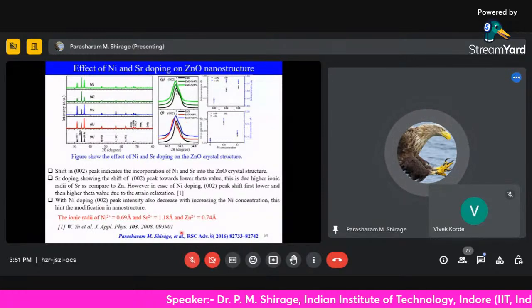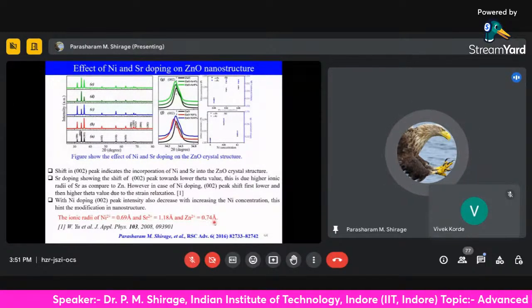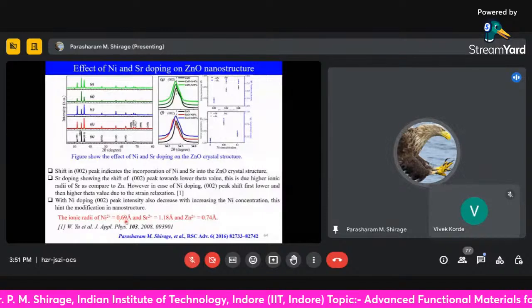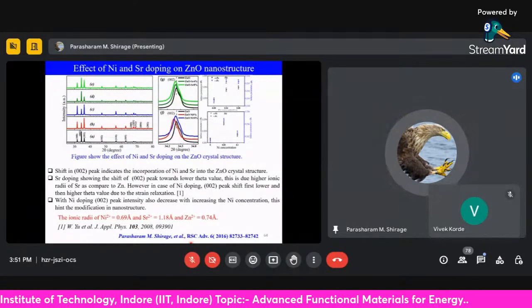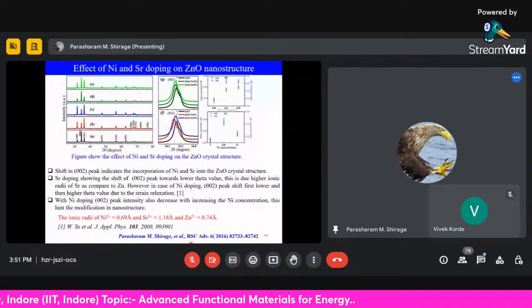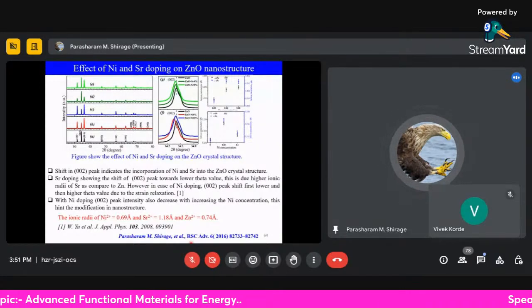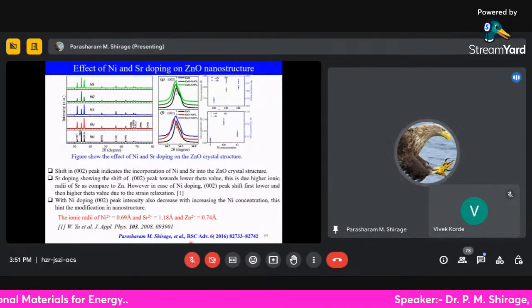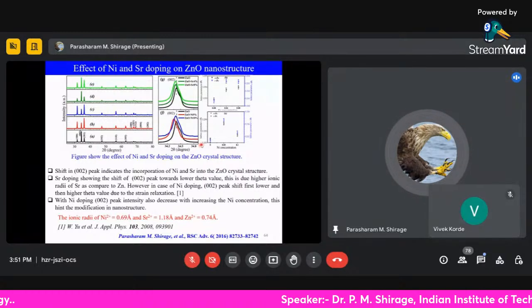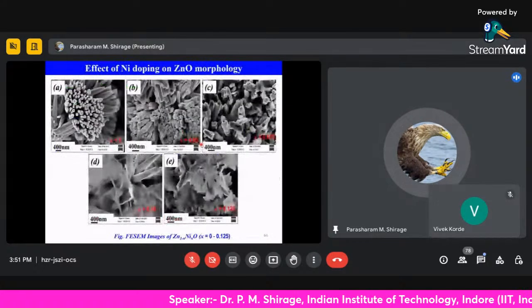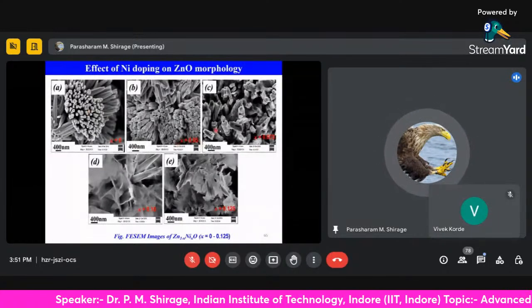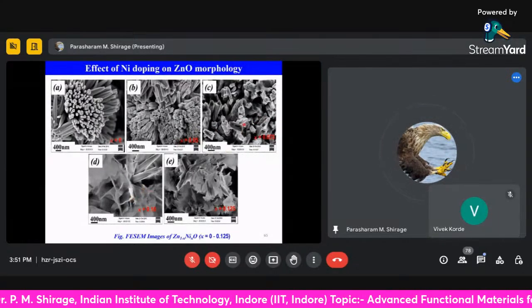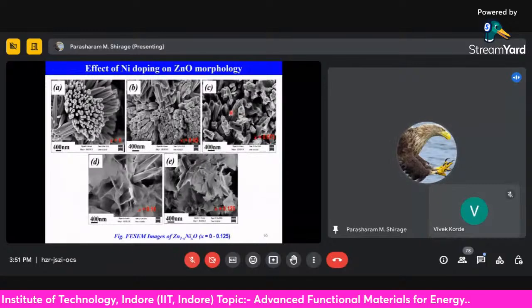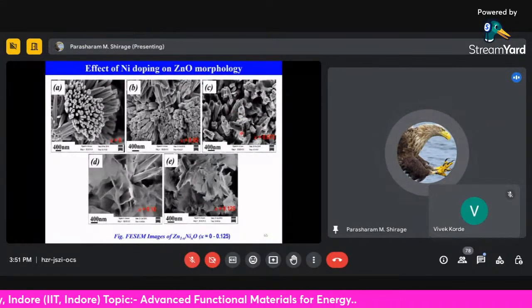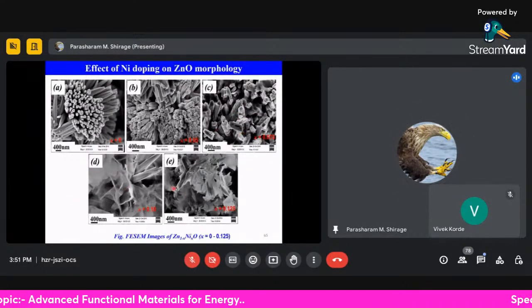But in case of nickel, we are replacing 0.74 angstrom with 0.69 angstrom. Then it is expected that lattice constant should decrease, replacing a higher ball with a smaller ionic ball. But here this mechanism is not so simple because strain is playing a role. And that can be seen from this morphology study. This rod-like structure is becoming the plate-like structure. This is an intermediate state. You can see that this rod-like structure is becoming two rod-like structures, and that plate is connecting, and it becomes a completely plate-like structure.